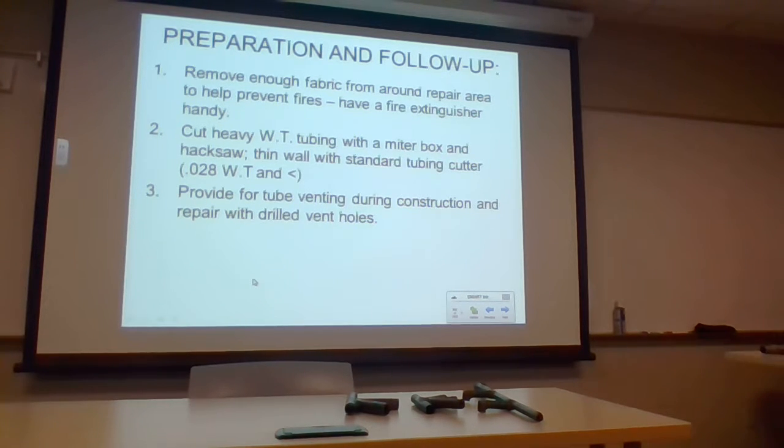Also, you should know this too. When tubing is assembled, it's sometimes possible to have air trapped in the tubing structure. And as you're welding, the completion of that weld is going to be almost impossible because as the air is expanding, it's trying to escape from the tubing. So what they do is they provide a vent hole in a lot of tubing as part of either construction or repair. And then after the welding has been completed, they'll use a drive screw to close the hole off. I'll talk to you more also about protection on the inside of the tubing to prevent rust.